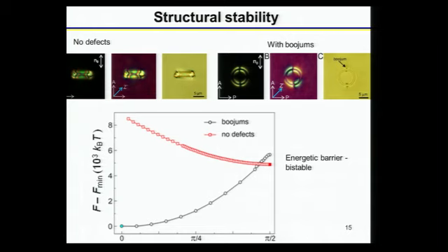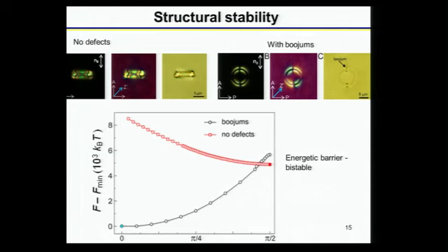So you can see in here the dependence of that free energy as a function of angle between the ring plane and far field director. And so you can see that the defect-free structure is of lower energy when they are perpendicular to each other, indeed, as we saw in here, right? But the global minimum is still the state with 4-point defects that you can see in here.